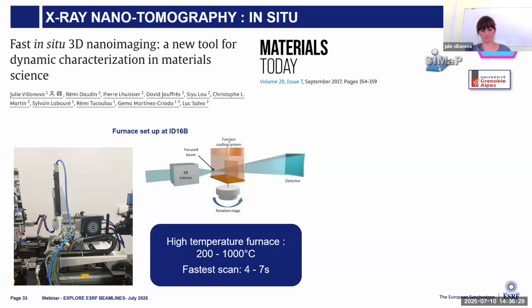So the first sample environment that has been designed at the beamline, in collaboration with the SIMaP at the UGA Grenoble, was a high temperature furnace that is still in use. You can heat up the sample from 200 to 1000 degrees while you are performing scans. And as you can see here on the schematic drawing, the sample is rotating independently of the furnace, which can be put down and up on the sample. And also, as it's maybe not so clear in the images, the furnace will move also with the sample, meaning that you can perform the multi-scale measurement as well.